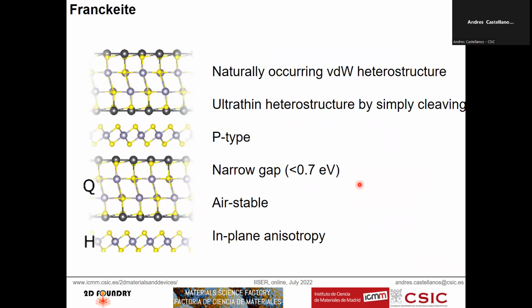So to finish with Franckeite, this bonus track: Franckeite is a natural van der Waals heterostructure or superlattice. It's a very simple way to fabricate a superlattice by just mechanical exfoliation, and it's a good alternative to black phosphorus because it has a narrow bandgap, is P-type, but is air stable. And as an example of what happens when you explore new, unexplored materials, we found something we didn't expect. We didn't expect to see an in-plane anisotropy, and we found out that just this weak interaction between these layers is strong enough to modify locally the position of the atoms and induce this in-plane anisotropy.